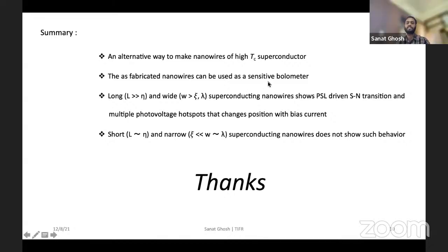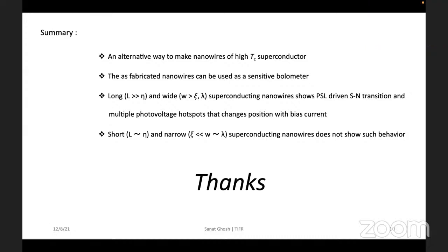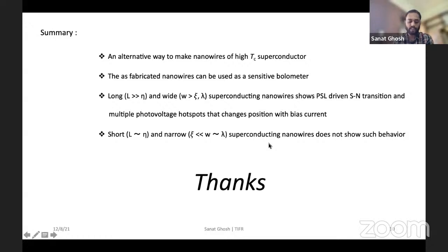Thanks for asking the question. The advantage of using BSCCO is that the nanowires used as bolometers are usually of low TC, so to operate those, you have to go to very low temperature, possibly with liquid helium. BSCCO has a TC of 85 Kelvin, so you can use a detector which can operate at liquid nitrogen temperature. The other question is how thin the nanowire can be. So far we could achieve a nanowire width of 300 nanometers, but we believe that this can be pushed to an even lower limit if we take some extra steps.